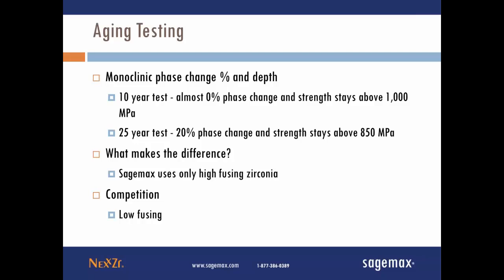within the industry and within aging testing is what's called high fuse or low fuse zirconia. Sagemax uses a high fusing zirconia, which means the optimal temperature for sintering is around 1500. Our competition is using what's called a low fuse zirconia, where the max recommended sintering temperature is 1350. I wanted to also mention here that with low fusing zirconia, there are no built-in error factors. In other words, if it's fired too low or too high, the material loses its integrity. Whereas with high fusing zirconia, very similar to high fusing porcelains, you have a built-in range where the material will still retain its integrity and strength as well as translucency.